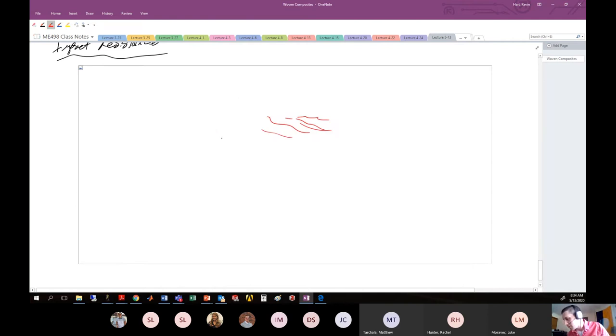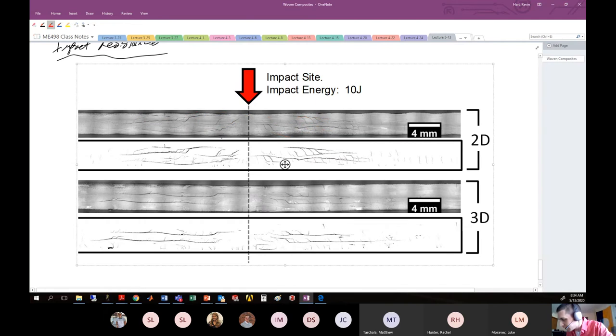You can see some damage modes that you're kind of familiar with at this point. Here's a long delamination that runs inside of the piece. You have here these 45 degree angle cracks. These are called shear cracks that form from the impact, et cetera, et cetera. The idea is that you can take this image and skeletonize it using some computer algorithms, which I had to write when I was in graduate school, to get you the damage profile, or the damage inside of that cross section.